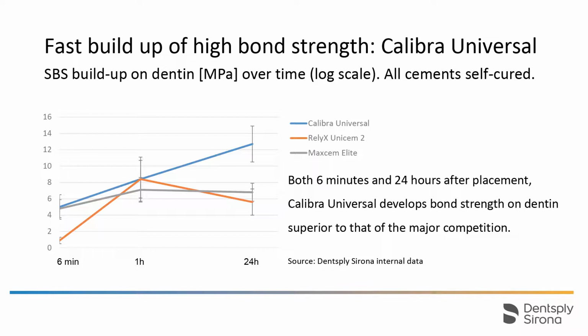After 6 minutes, Calibra Universal has developed a bond strength of around 5 megapascals. 1 hour after placement, the bond strength exceeds 8 megapascals, and 12 megapascals after 24 hours. RelyX Unicem and Maxcem Elite build up bond strength much more slowly. Their final bond strength after 24 hours is also significantly less.